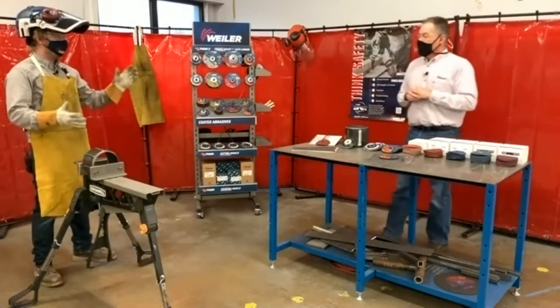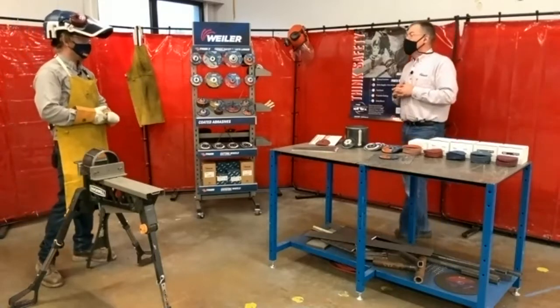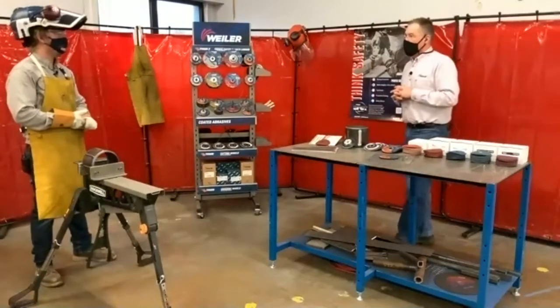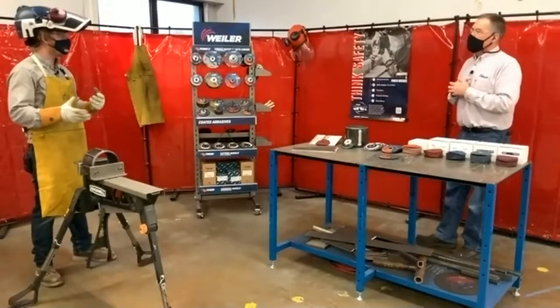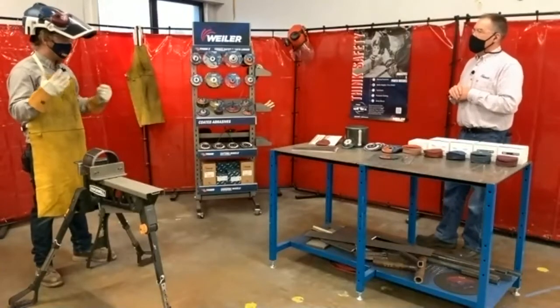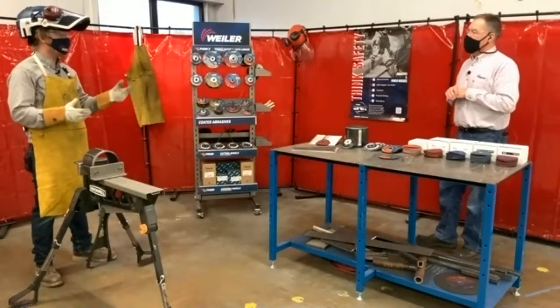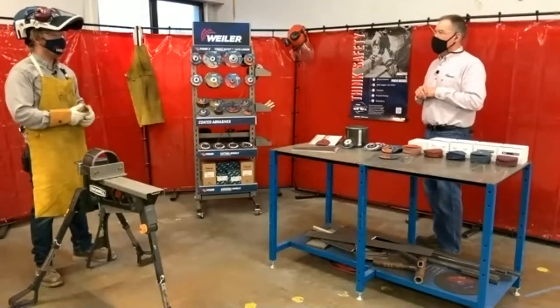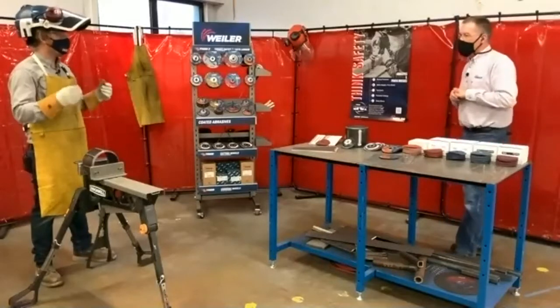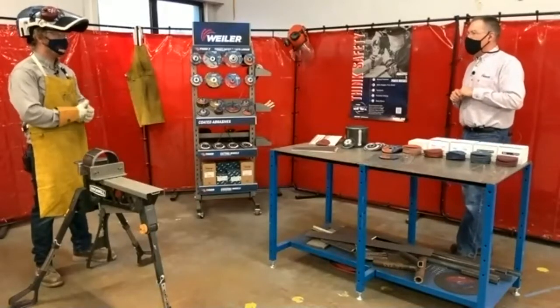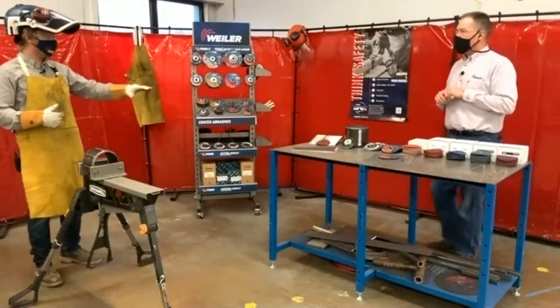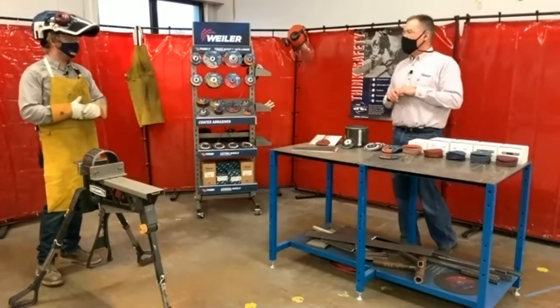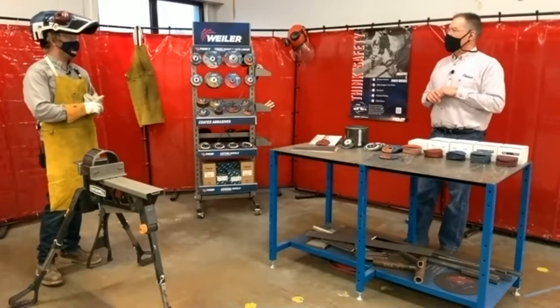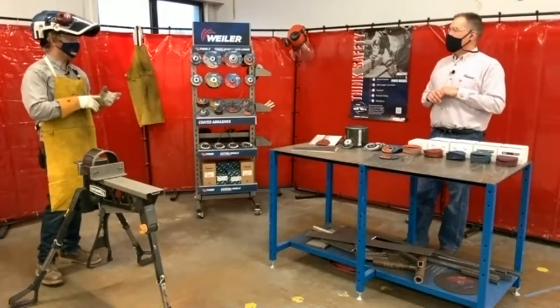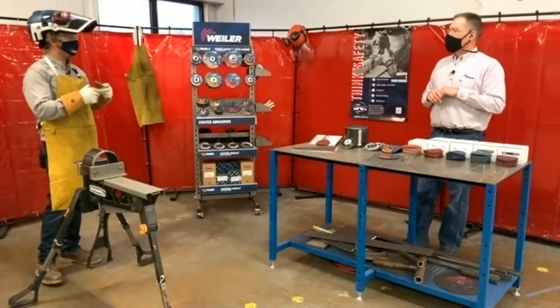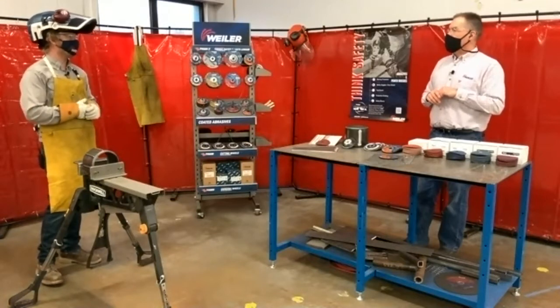Right, and before top coat for aluminum specific products, a lot of people were using the aluminum oxide grain, but they were putting waxes, some sort of lubricant on it. That gets on the floor, it gets all over you, and not to mention it's a secondary process to clean with some sort of acetone or paint thinner, which is not great for your skin, not great for the material. So using an aluminum specific top coat product like the aluminum RFD, you're eliminating secondary cleaning processes, and you're keeping everything clean enough so you could go straight to weld after grinding with the product.